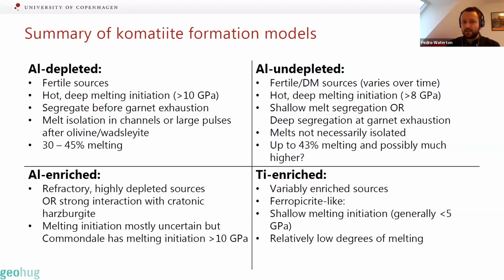Aluminium-undepleted komatiites: the old ones have fertile sources, the young ones have depleted mantle sources. They also have hot and deep melting initiation, at least greater than 8 gigapascals, some of them greater than about 10. And either there is shallow melt segregation or deep segregation at the point where we cross the garnet-out curve. We don't need to isolate the melts because we don't have to preserve a garnet signature in these. They show similarly high degrees of melting, with the possibility that some of them, this Barberton aluminium-undepleted komatiite, extend to much, much higher melt fractions. But again, we don't know what's going on there.